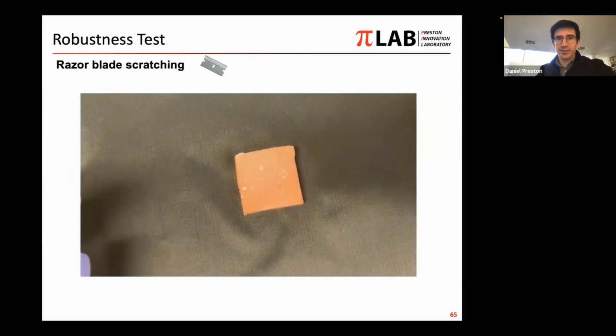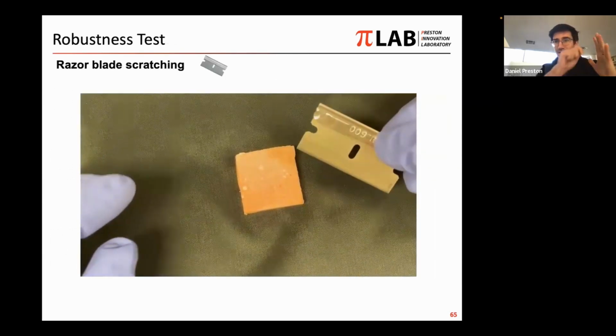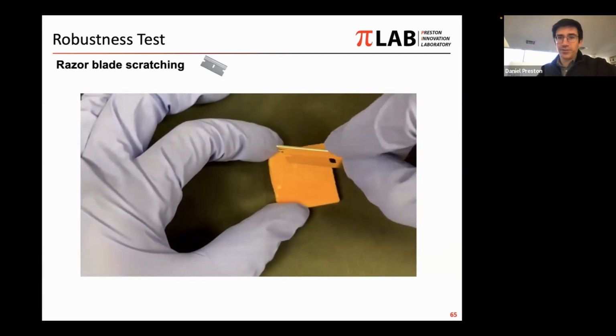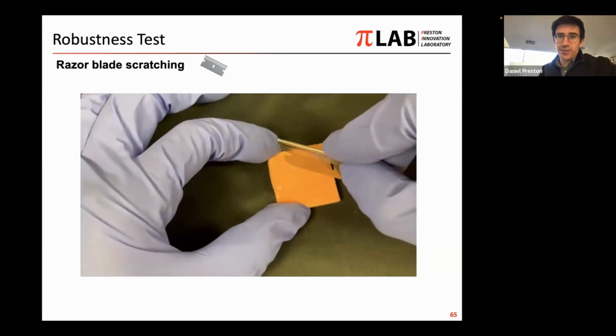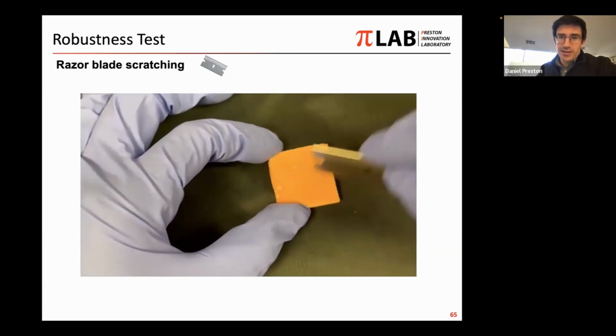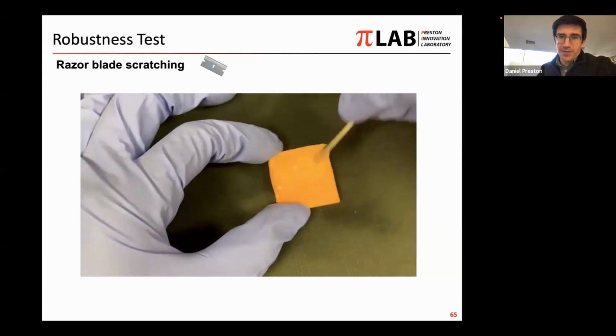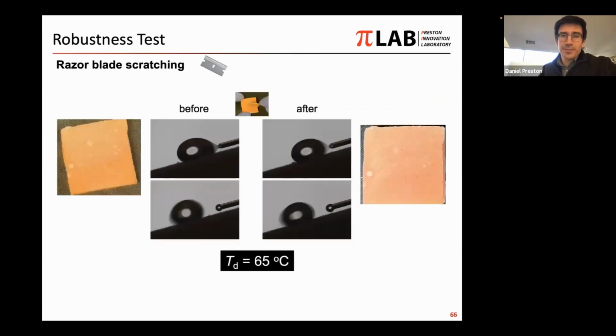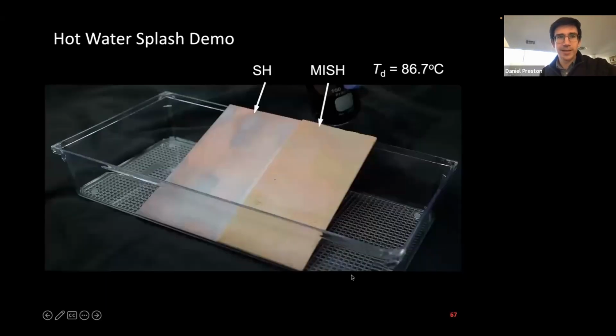We did some durability testing. We looked at the robustness in this case by scratching the coating surface with a razor blade. We can visually see some of the marks that form on the surface. After that, we looked at the departure size and found that it was not changed, even with hot water. This is water at 65 degrees Celsius on this scratched surface. So that was promising in terms of the robustness.